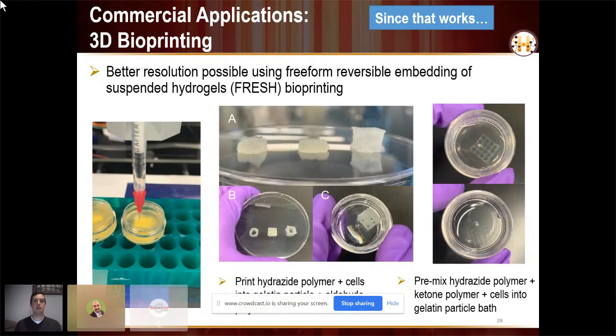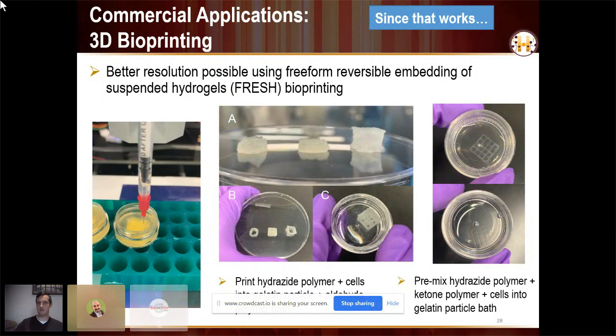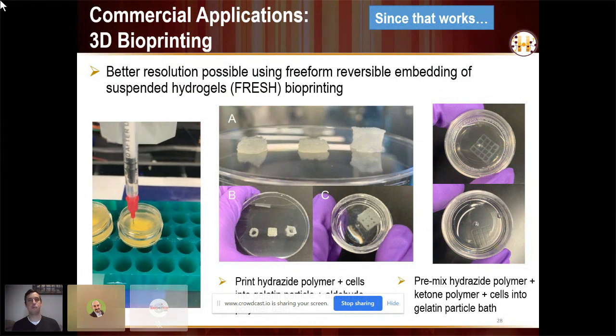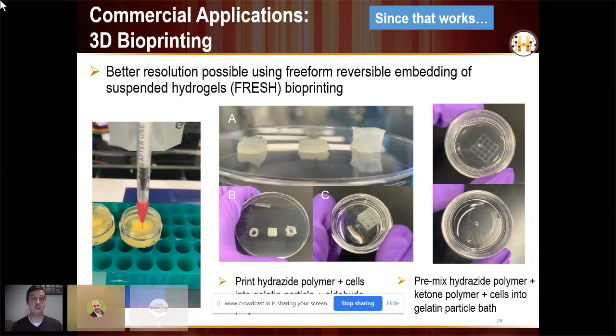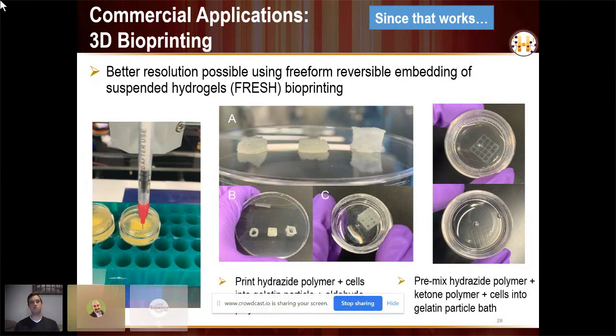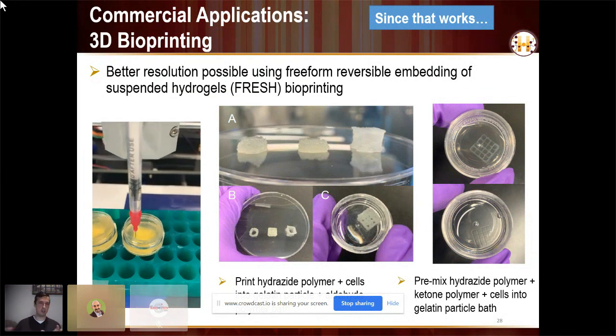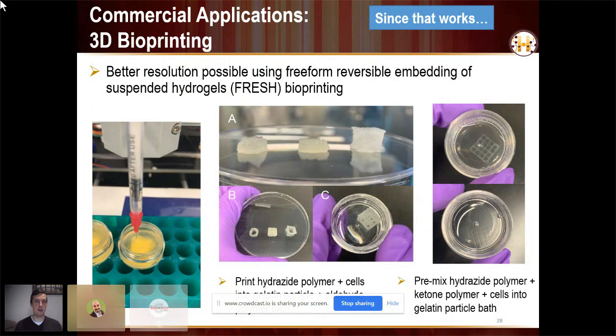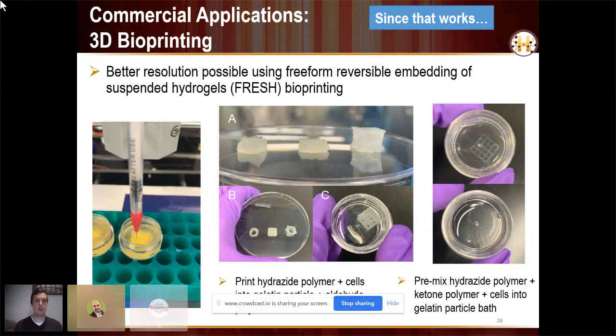The other thing we've been looking at, to try to build more 3D structures with this material, is freeform reversible embedding of suspended hydrogels, a fresh bioprinting strategy, where these hydrogels are printed into a gelatin microparticle bath. This was really pioneered by Adam Feinberg at Carnegie Mellon. And this helps to physically support the gel as you build it. So it's much easier to build 3D structures in these supported bioprinting strategies.